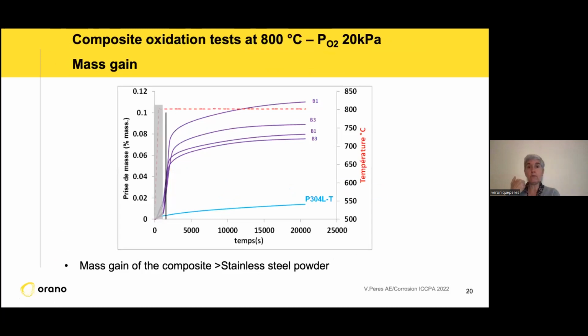If we do the treatment under air at high temperature, 800 or close to 800, under oxygen, you will see two things. We have in purple here different tests we have done with the composites. It's not so reproducible, but it's quite the same behavior. So you can see here a very big mass gain of these systems. But if you look at this blue line, which is the powder mass gain, it's very, very low compared to this composite behavior. So why does this happen?